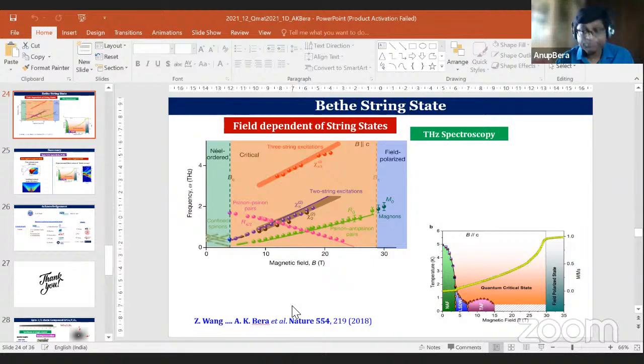Yes, I agree. As I presented, in zero field this is a compound which has a weak interchain coupling, and weak interchain coupling basically does not lead to the quantum critical state. Instead, we see the ordered state at very low temperature, but at higher temperature it is in the critical state, meaning the spins are not ordered, but they are highly interacting spins. But that could be a thermally fluctuating state.